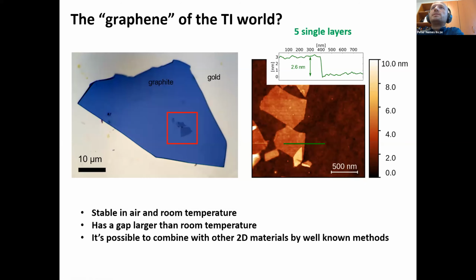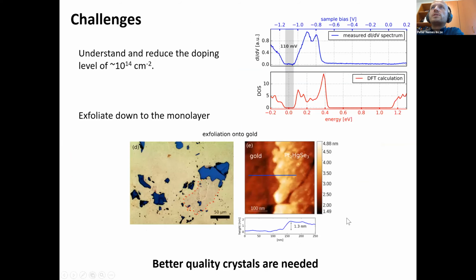So as a few last thoughts, of course, I have to mention challenges and problems. And one of the problems in this case is that we have this very large level of doping of the order of 10 to 14, which has to be reduced for this material to be used in, for example, a transport measurement. I haven't included here in the slides, but if you look at very thin crystals of these 5 or 10 monolayers, this doping becomes much less. So this could be an indication that indeed some non-stoichiometric impurities or something very similar is at fault here.